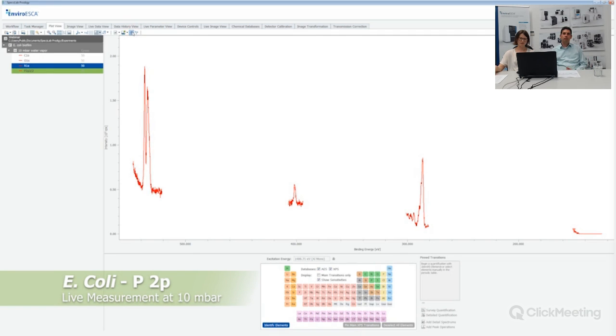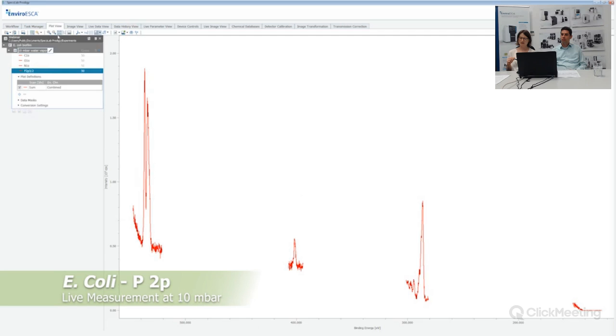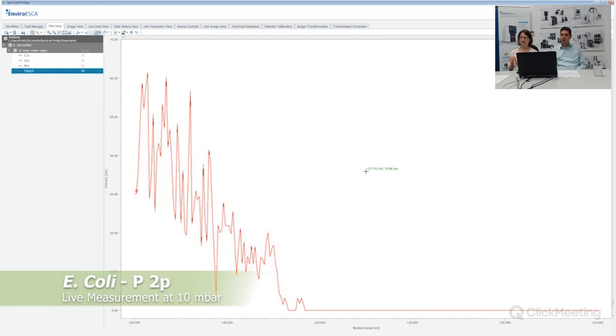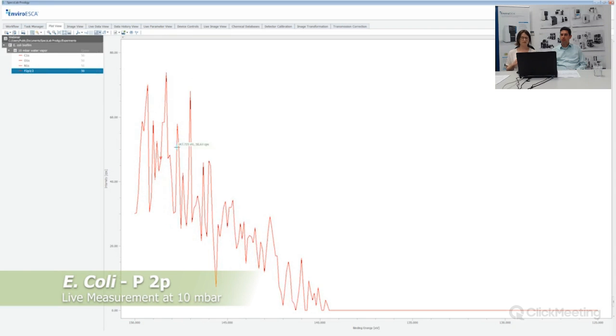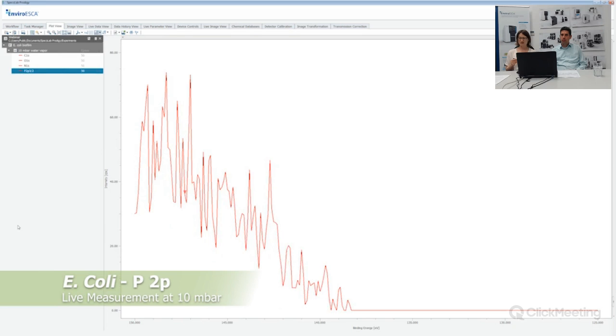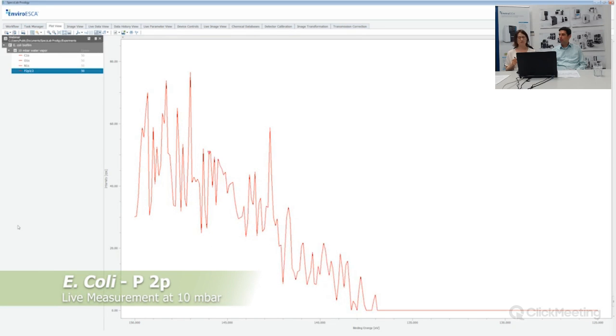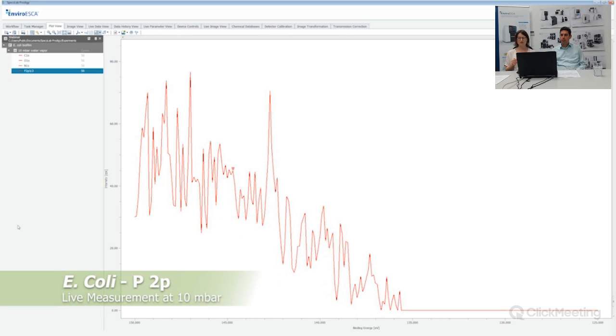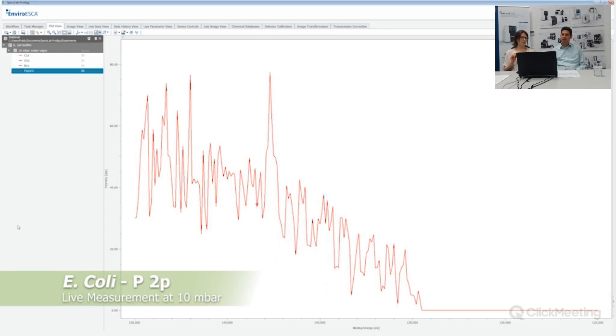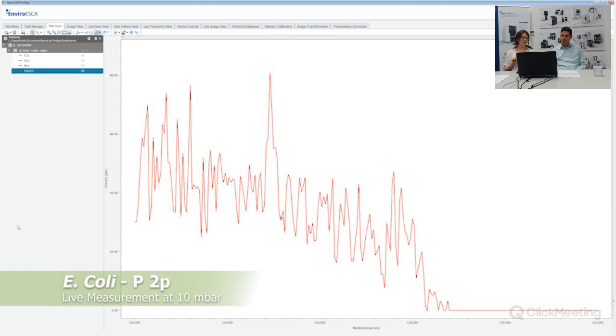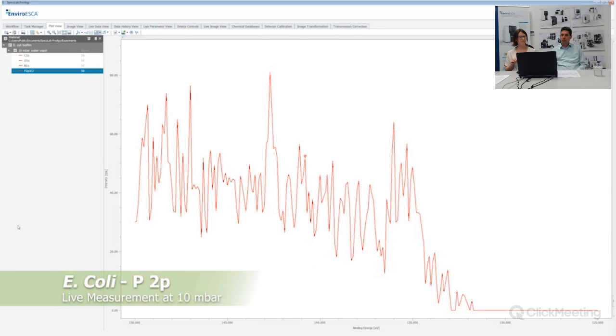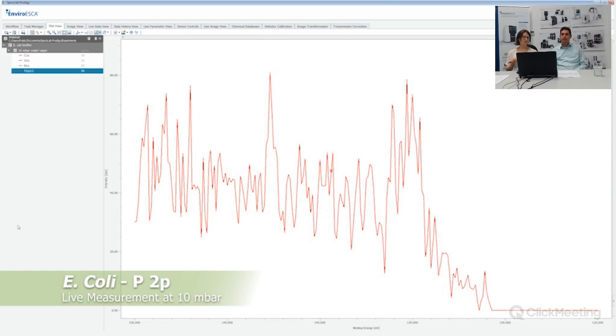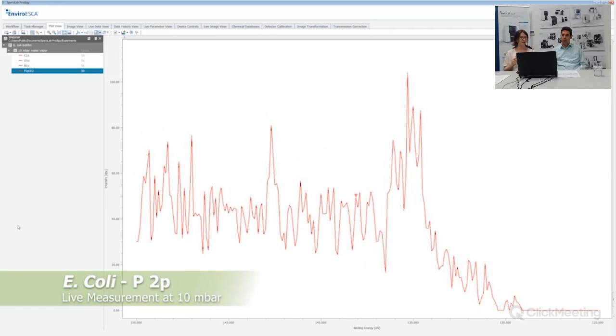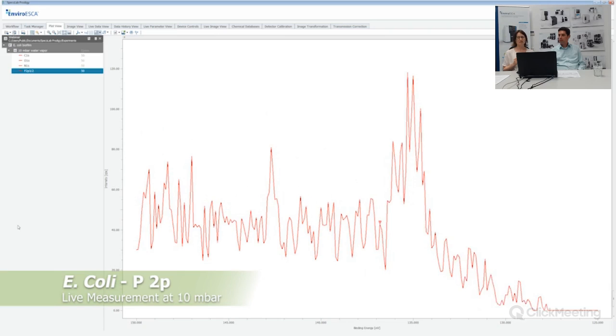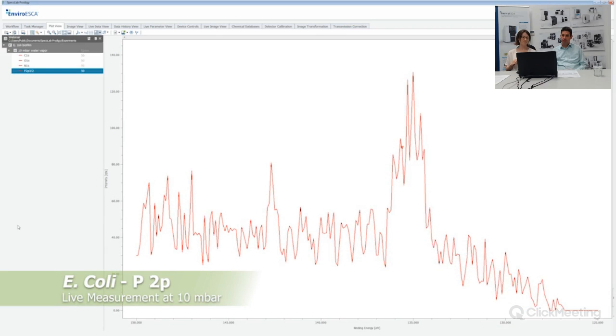For data analysis, I often look at the atomic ratios between carbon, oxygen, nitrogen, and phosphorus. Very roughly, after you correct for sensitivity, the oxygen to carbon ratio is approximately 0.4. Nitrogen to carbon is 0.1 to 0.2, and phosphorus to carbon 0.01. So you really have a distribution there, and this kind of quantitative data you can also look up in the literature, where you have some review articles on freeze-dried bacteria, where you can compare the elemental composition to our results.